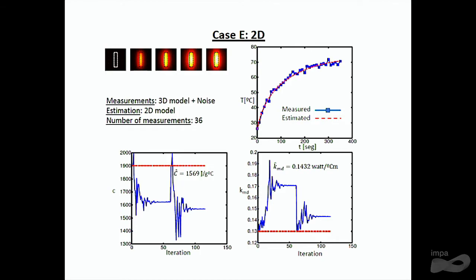In this case, we have a pretty reasonable conversion to values that are close to the real ones, as you see. So we may say that a model that in 2 dimensions is a good candidate to estimate parameters from real data and to have these parameters converge to values that are quite close to the real ones.